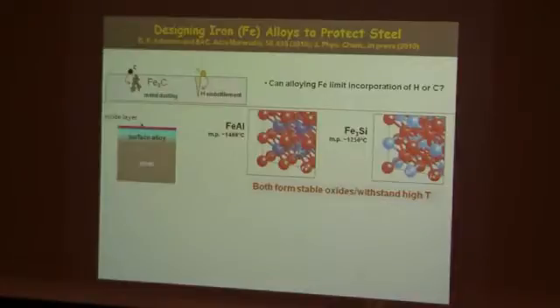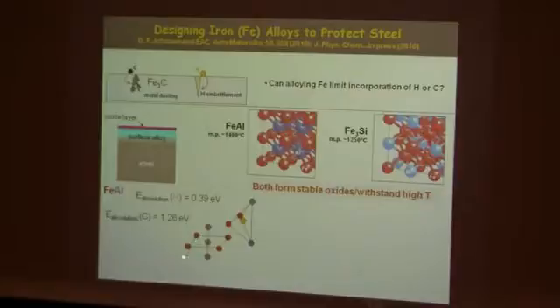And so what we did was to investigate how hydrogen and carbon might get into these and compare them to how they behave going into steel itself. And don't worry about the units here, just think about the numbers. What these are is an indication of the amount of energy you have to put in to dissolve hydrogen. This is showing a hydrogen right here. It likes to sit in tetrahedra, actually, of metal atoms. And this is the amount of energy. It's uphill, actually, to put hydrogen into iron aluminide, and even more uphill to put carbon into, here's the carbon shown in gray. It likes to sit in this other kind of site surrounded by 6 metal atoms, and it's even more uphill.